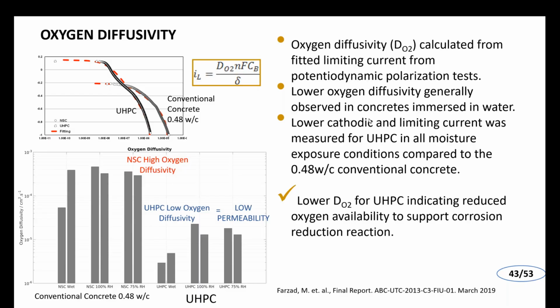The 3 on the left represents the normal strength concrete at different moisture conditions, and the 3 on the right are for UHPC for different moisture conditions. And invariably, the UHPC, whether it's in a dry environment or wet environment, has much lower transport of oxygen through the concrete compared to that of a conventional concrete. So this is good verification, again, verifying that the concrete has low permeability, but also that gases have a more difficult time penetrating this material, whether it be oxygen, and similarly, it can be alluded to CO2 as well. So UHPC can be a useful material to prolong the time for which CO2 can penetrate through the system.